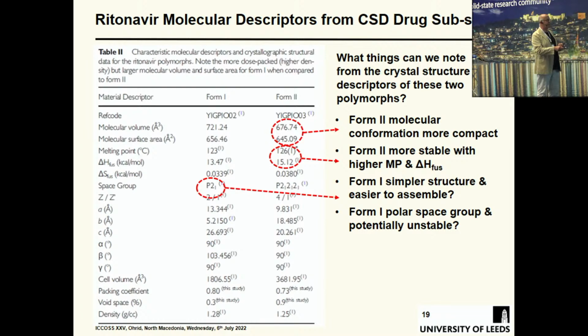So when you see something, and we were discussing that at posters, in a simple space group like P21, you can see that there's only one symmetry operator, and the self-assembly process is going to be a bit easier. And then you've got the stable structure as P212121, so you've got 4 symmetry operators to get those intermolecular interactions right. Also, form 1 is a polar space group, it's P21. And in general, structures don't like polar structures. It's not a thing that nature likes. So if I see a polar space group, I think, that'd be interesting. I don't know why, but it just tickles something in the back of my mind.